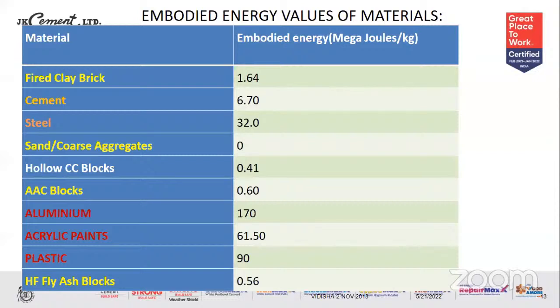Just a chart which shows EBEs of different products. As I mentioned, fired clay bricks is 1.64, whereas AAC block is almost 1/3. Just look at those alarming and screaming red values. Aluminum is as high as 170. Acrylic paints, which we always passionately choose for our new houses, is almost 62. Plastic 90. Just look at steel. Anyway, it cannot be avoided. 32. Cement cannot be avoided, but if we go for blended cement, it could be significantly lower, as low as 3.5 to 4.